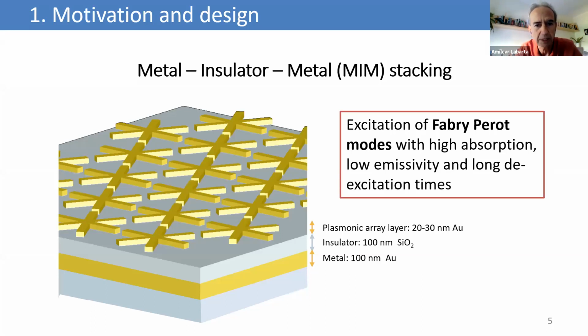The active plasmonic structure is grown on top. Then there is a separator in the middle, which is an insulator. And above, there is a continuous layer of gold that acts as a mirror, okay? The thickness of this layer is thick enough as to ensure no transmission. At least this is the schematic of the first systems that I am going to show you.